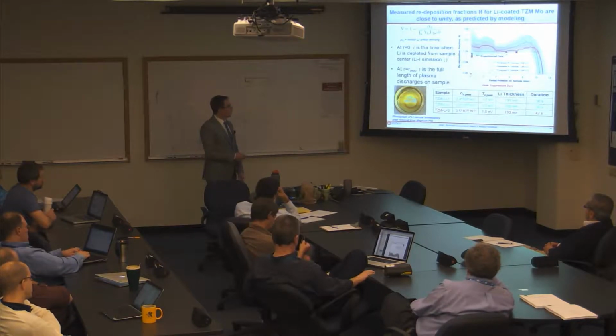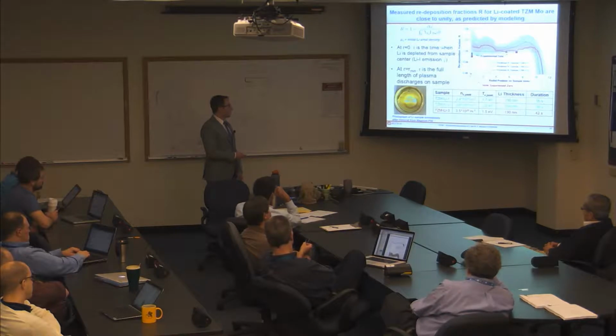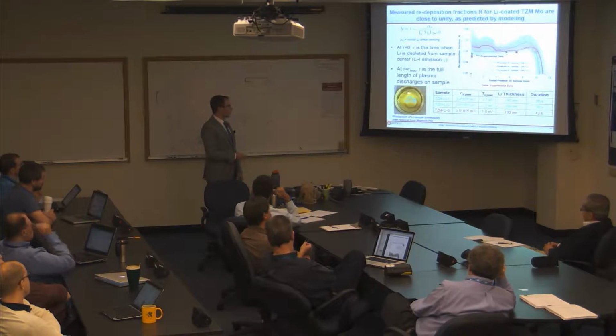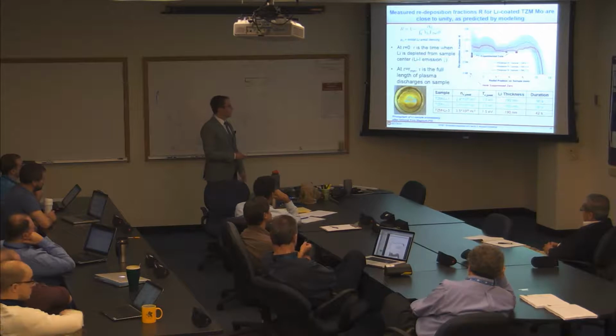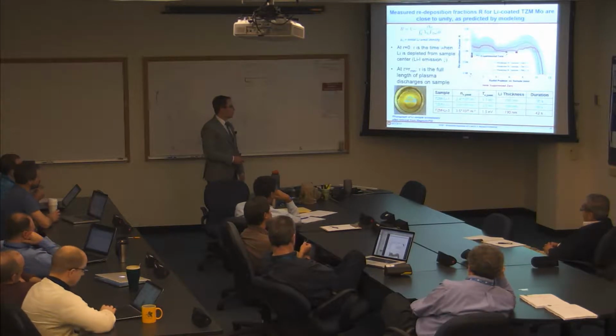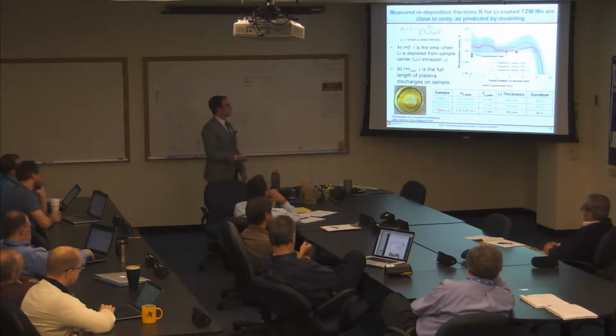And then these measurements out here near the middle of the sample are, you take the sample out after the plasma exposure, and you see that there's some circle in the middle of the sample that has no lithium on it, and then there's some portion here that still does have lithium on it. So the radius here is basically the minimum radius that still has lithium on it, and so you say, okay, what was the total lithium fluence that I saw from this ring right here? And then divide that by the initial areal density, and that gives you a redeposition fraction as well.